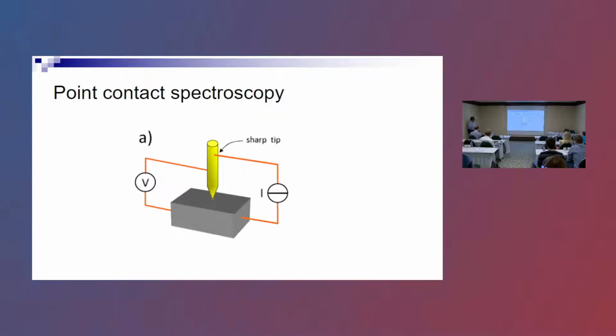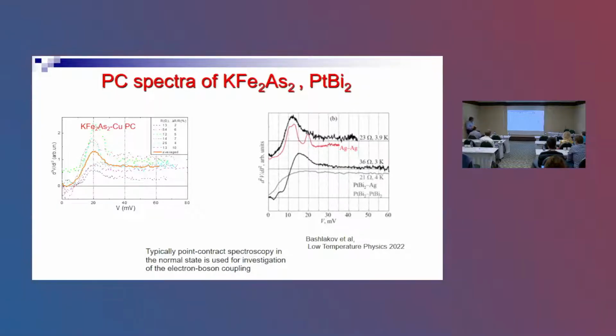Recently there was an additional experiment, a point contact experiment, in our institute. Point contact spectroscopy is the following: we take a very thin tip to the surface and measure the resistance. One can get information about electron-boson coupling as the second derivative of the voltage over the current, which one can show is directly proportional to the electron-phonon coupling, alpha squared F. That was the main motivation for this investigation, just to see how strong the electron-phonon coupling is.